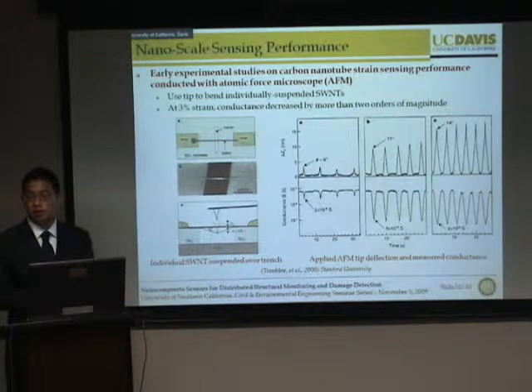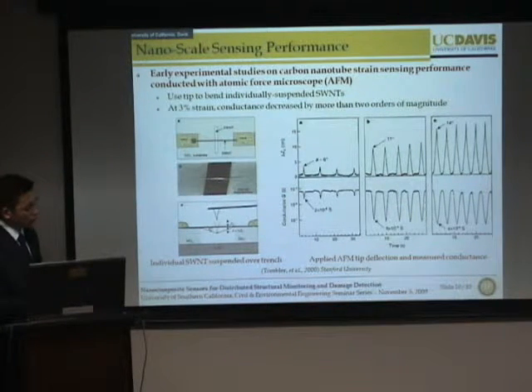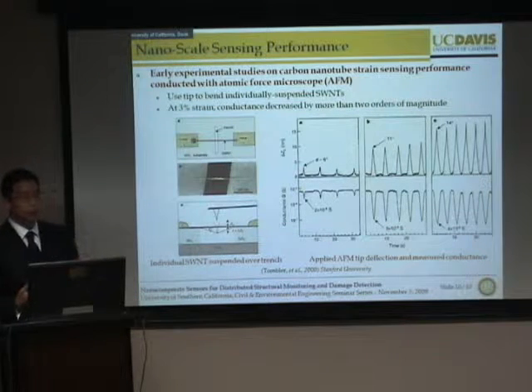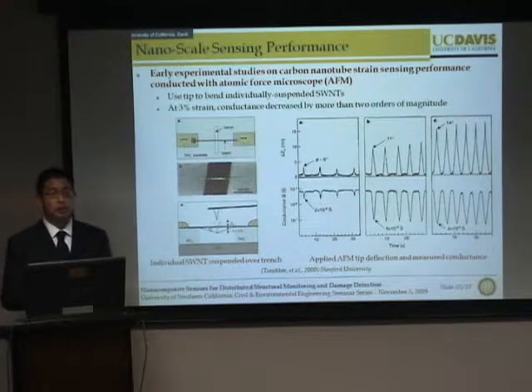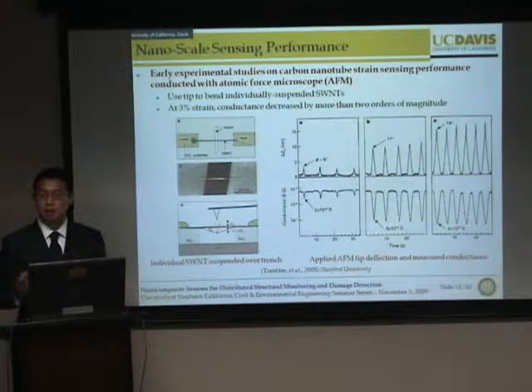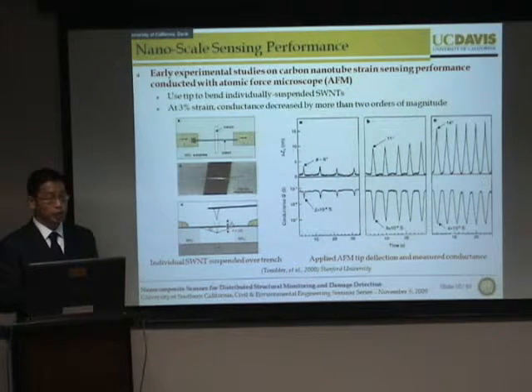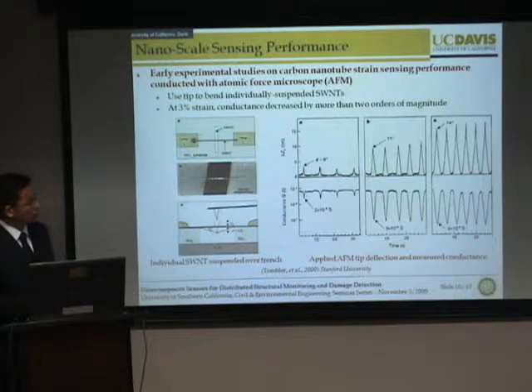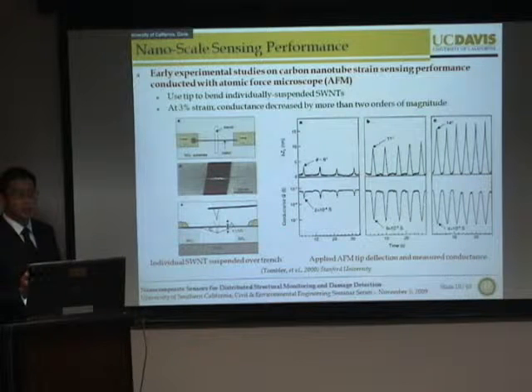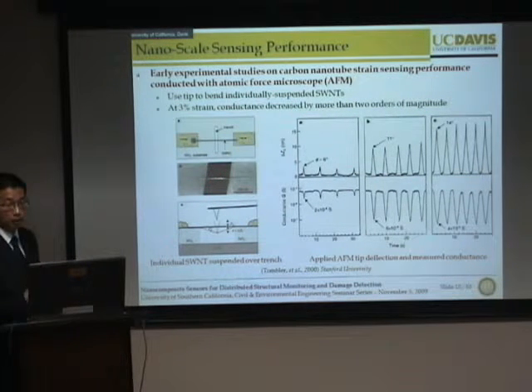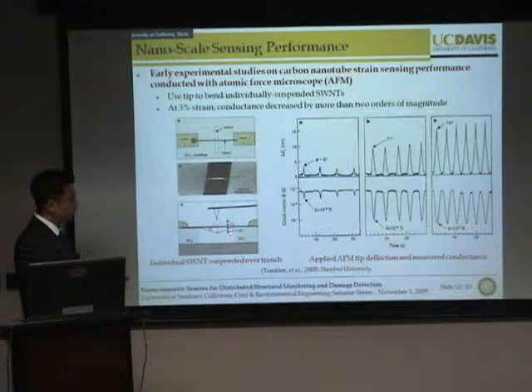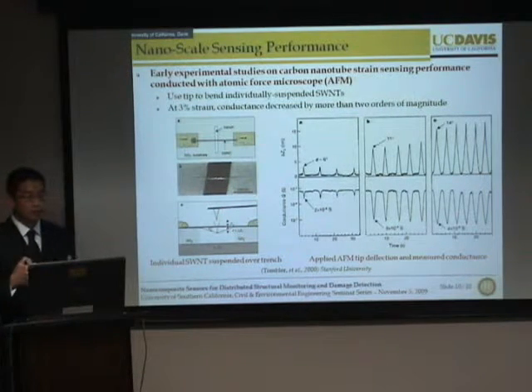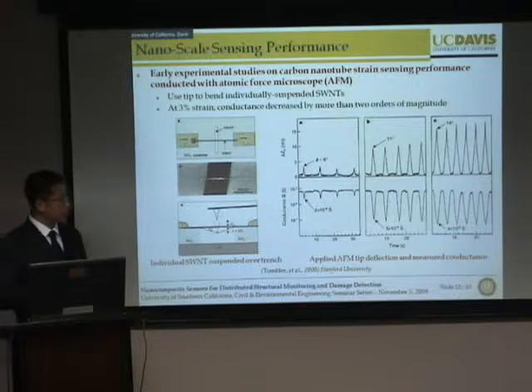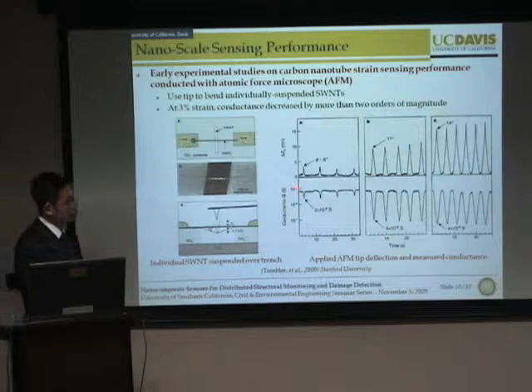Now, in addition to these impressive material properties, many researchers have also wondered whether we can use these carbon nanotubes directly to build a sensor. And in fact, Hongjie Dai's group at Stanford University have pioneered this work to look at the piezoresistive response of carbon nanotubes. And that is whether the electrical properties of carbon nanotubes will change under applied strain. So what they did in their study was they were able to isolate an individual carbon nanotube and then suspend it over a patterned silicon trench. Then, using an atomic force microscope tip, they can apply 3-point bending to this carbon nanotube while simultaneously measuring the vertical displacement that they apply, as well as the change in conductivity, G.